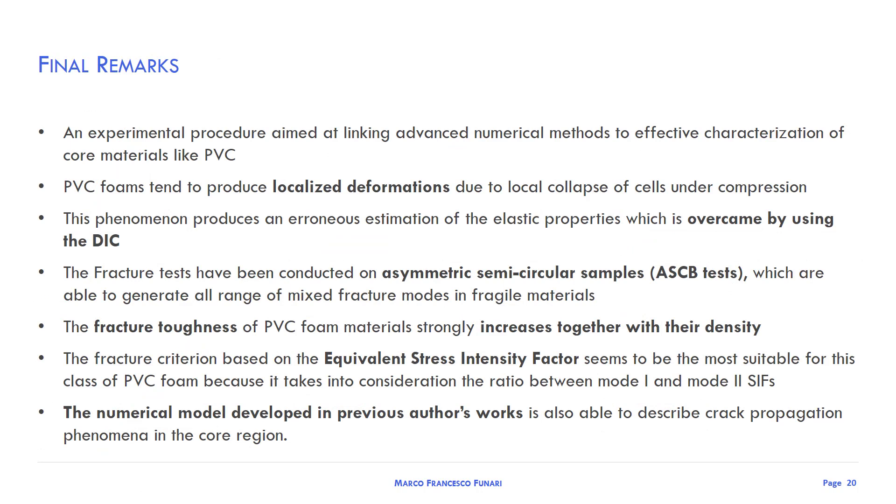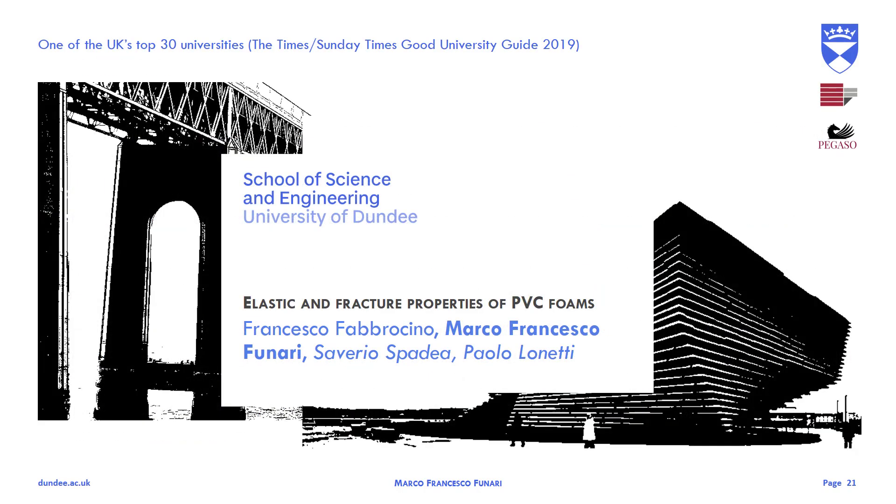Now just some conclusions. An experimental procedure aimed at linking advanced numerical methods to effective characterization of core materials like PVC. PVC foams tend to produce localized deformations due to local collapse of cells under compression. This phenomenon produces an erroneous estimation of elastic properties which is overcome by using digital image correlation. The fracture tests have been conducted on asymmetric semicircular samples which are able to generate all ranges of mixed fracture modes in brittle materials. The fracture toughness of PVC foam materials strongly increases together with their density. The numerical model developed in previous author works is able to describe crack propagation phenomena also in the core region. Thank you very much for your kind attention.